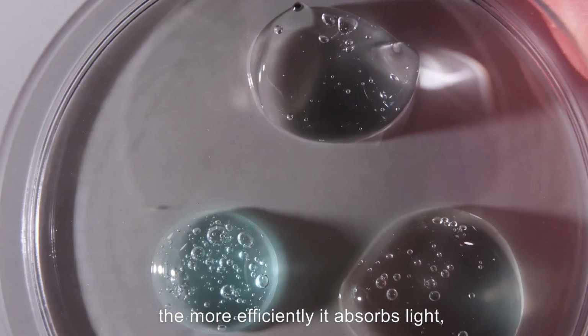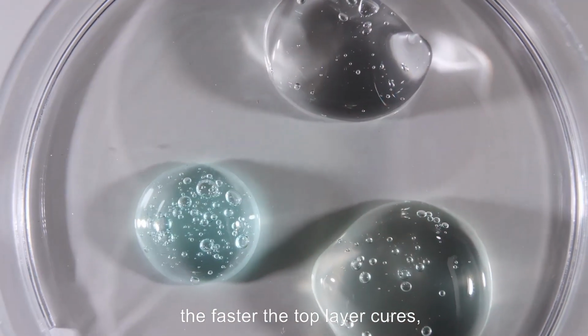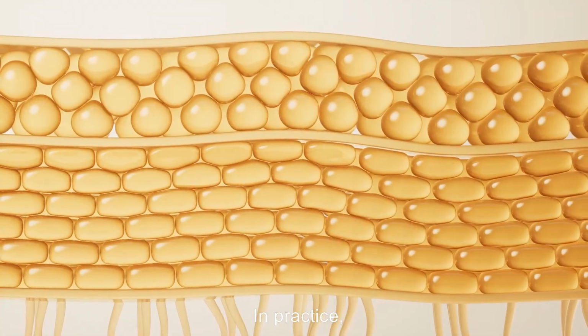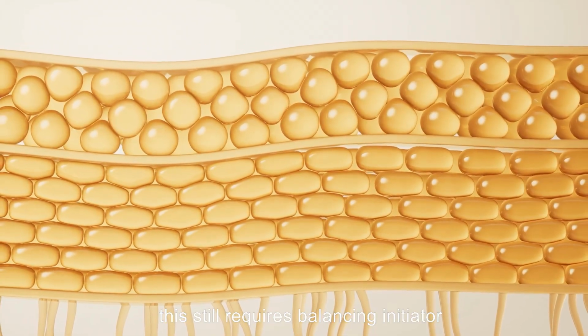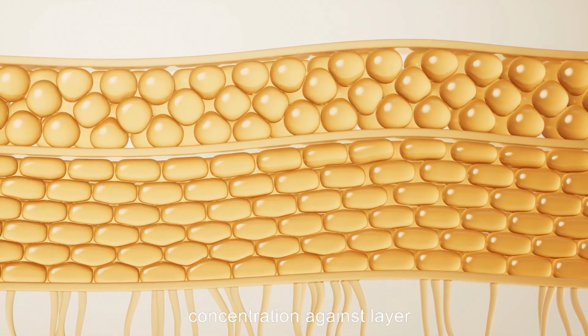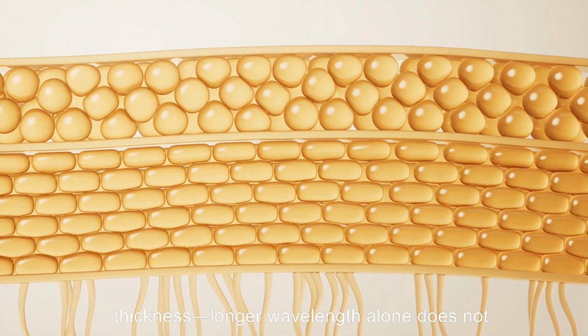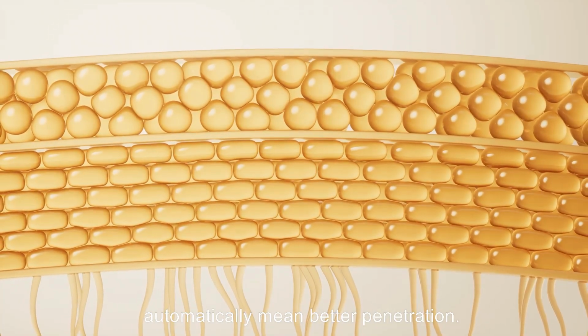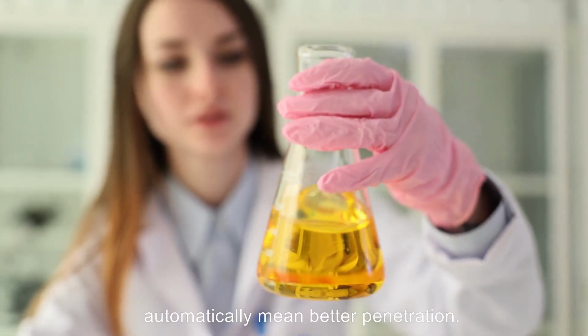The more efficiently it absorbs light, the faster the top layer cures, but the more readily it intercepts the light and leaves the bottom undercured. In practice, this still requires balancing initiator concentration against layer thickness. Longer wavelength alone does not automatically mean better penetration.